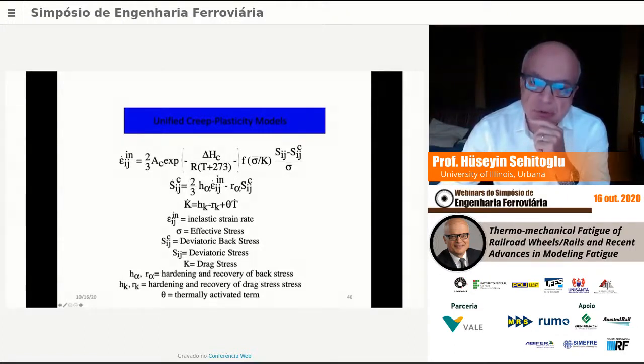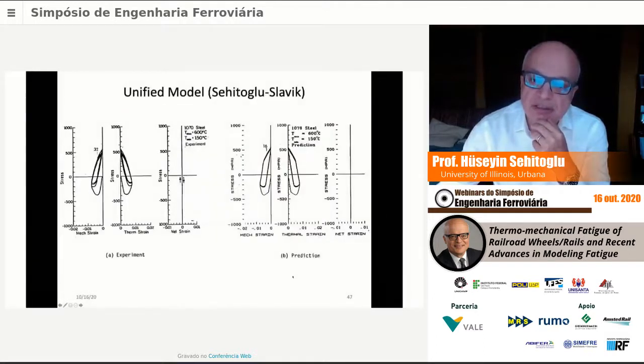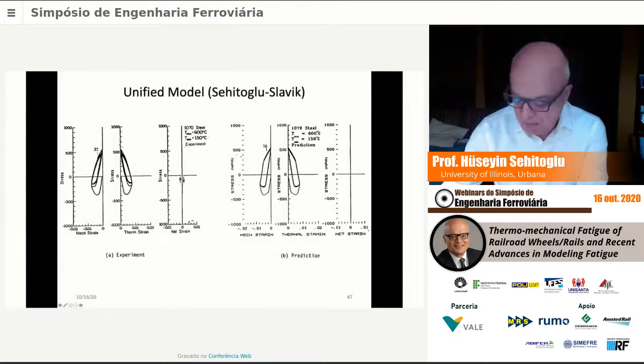It has an evolution, which has a hardening and a recovery. K is like a yield stress, the normalizing stress. That has a hardening and a recovery because, in the case where there is spheroidization going on in the 1070 steel, this term, the RK term, will not be zero. It will be significant. If there's cyclic hardening, it will be reflected in the HK term. This H alpha and R alpha are also obtained directly from experiments. So these are hardening and recovery of the back stress.